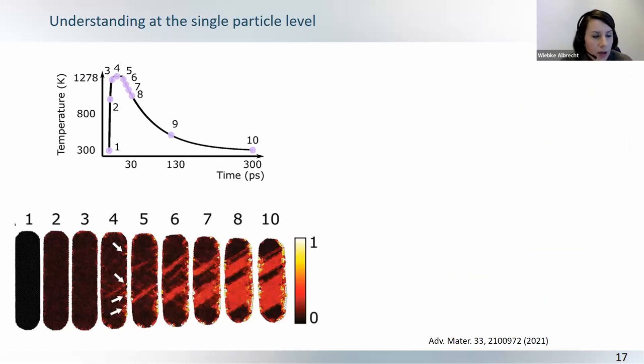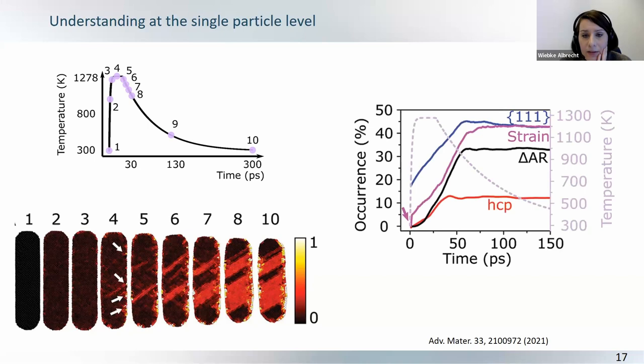And why the twinning occurs is coming from the surface. So, this silica confinement leads to propagation of surface defects. So, the strain, this is the strain in the system. And you can see that it starts from the, due to surface diffusion at the silica confinement at the surface, and then propagates through the crystal by formation of these twinning defects, together with the locally melted atoms. So, all of these are basically intertwined and occur together.